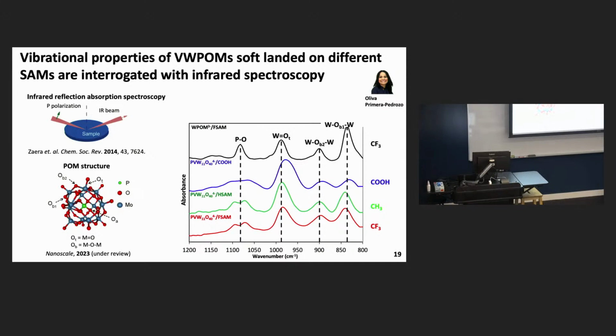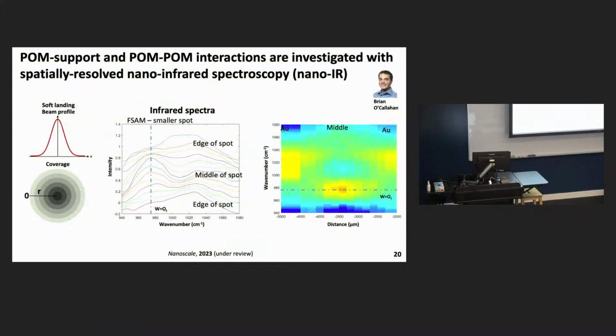And what I'll draw your attention to are the shifts in the vibrational bands of this terminal oxygen group. You can see here it is quite pronounced on the carboxylic acid terminated monolayer. And this is also manifest in the bridging oxygen bands shown here and here. So what we learned from this basically is that the methyl and CF3 terminated layers have some effect, although small, on the vibrational modes, whereas the carboxylic acid terminated layer substantially distorts those terminal tungsten oxygen bands. So this would potentially give a pathway basically for loss of coherence through vibrational coupling to the surface.